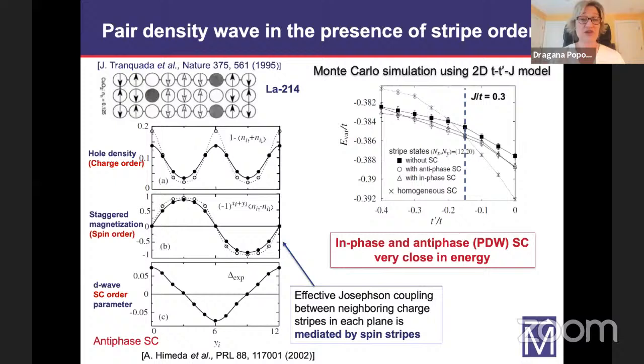So the paired density wave, actually, was shown quite some time ago in this paper here that in the presence of stripe order, it may be a ground state or very close in energy to the ground state. So here again is the sketch of charge and spin stripes, and the bottom panel shows the superconducting order parameter, which is most pronounced in charge stripes, but the phase is reversed between adjacent charge stripes. So this paired density wave, or the anti-phase superconducting order, was invoked later on in this paper